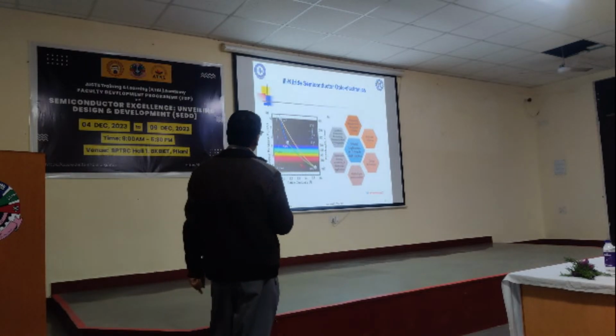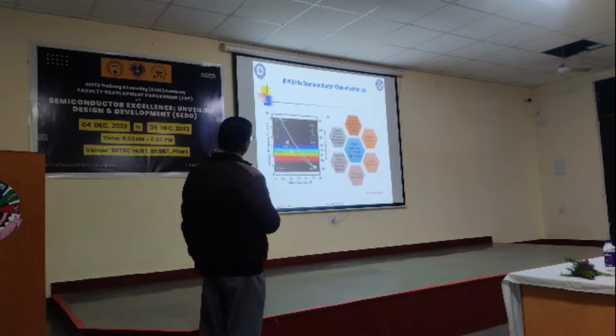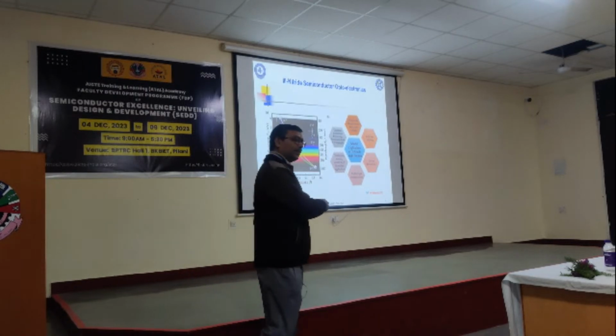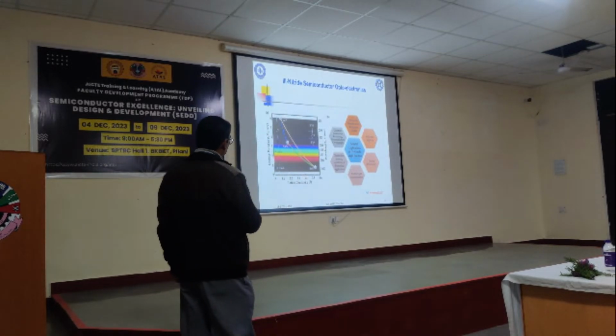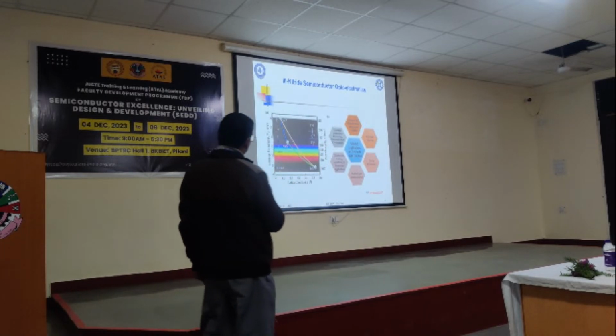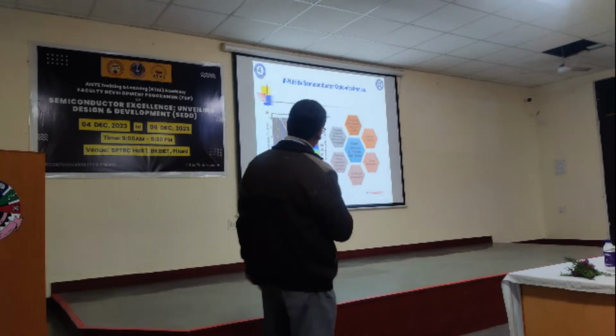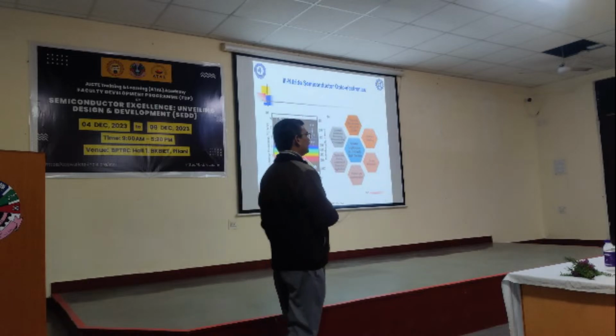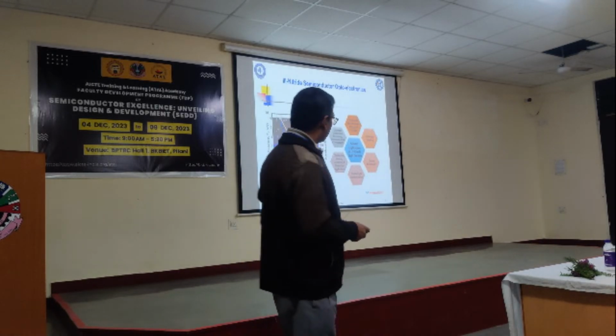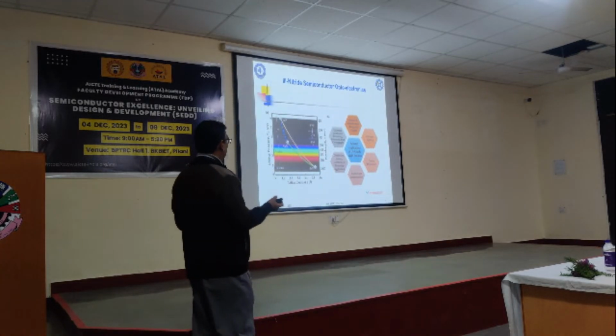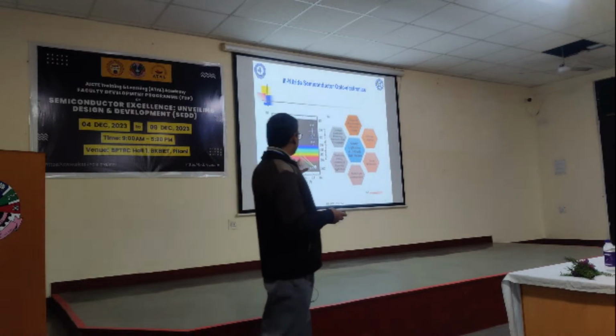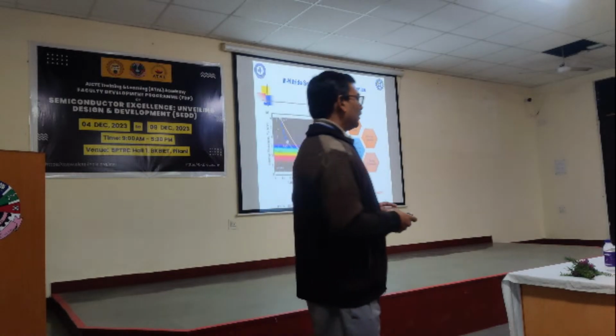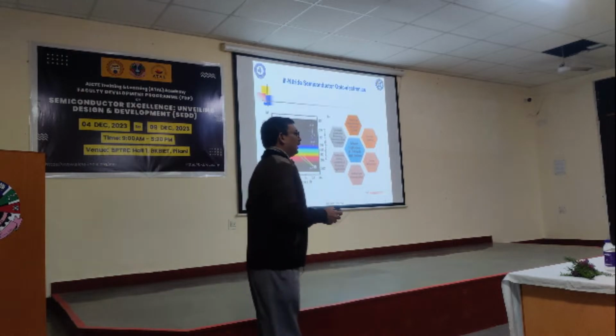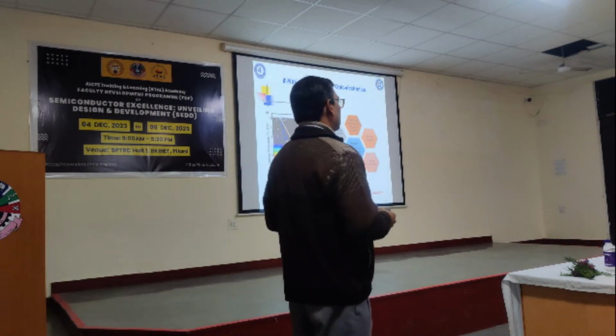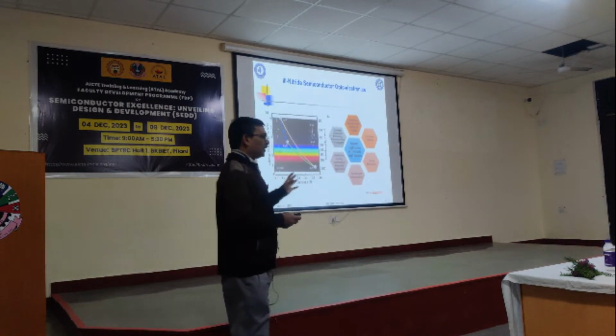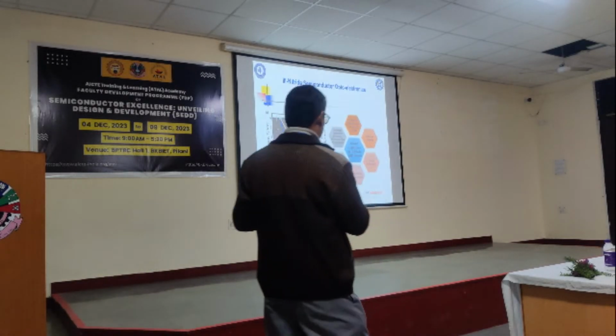Similarly, if we incorporate indium composition, the band gap will be lower and lower, but still all those are direct band gap. Starting from the visible range, towards the green range also it is possible. Again, high indium incorporation within that material is also a technological challenge. So beyond the infrared, it is very difficult to get the emission in that wavelength using gallium nitride or indium gallium nitride based material devices. Nevertheless, other materials, gallium phosphide or gallium arsenide phosphide, are very much efficient to emit the wavelength in that range.